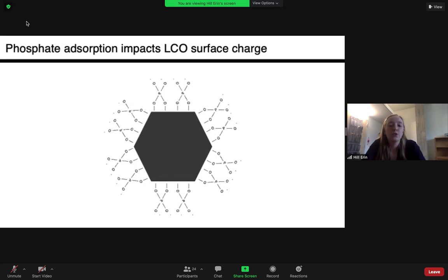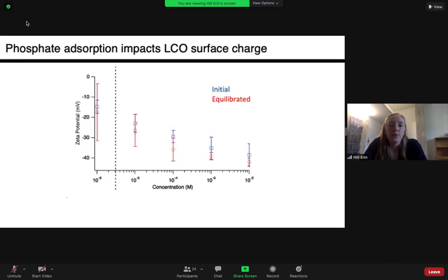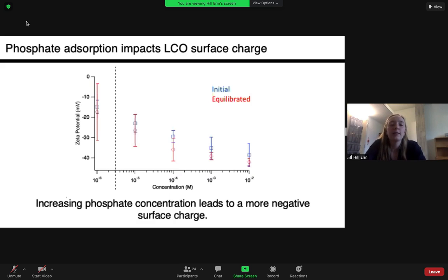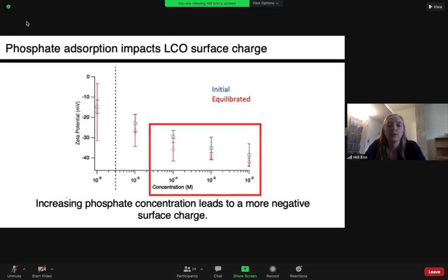My group made 5 solutions with varying concentrations of phosphate. And so they were first measured right when the LCO is added to the solution, and then again after 3.5 hours of sonication. After the second measurement, we see what we predicted. As concentration of phosphate increases, there's a decrease in the zeta potential. Particularly if we look at these last 3 concentrations, 10 to the minus 4 and greater, there's a zeta potential of magnitude 30 or greater, and this magnitude suggests that the LCO phosphate particles are stabilized through electrostatic repulsion.